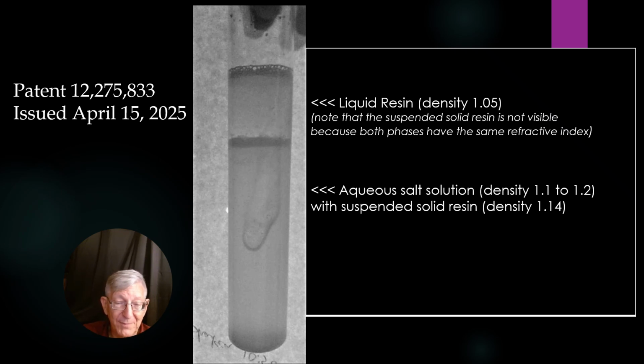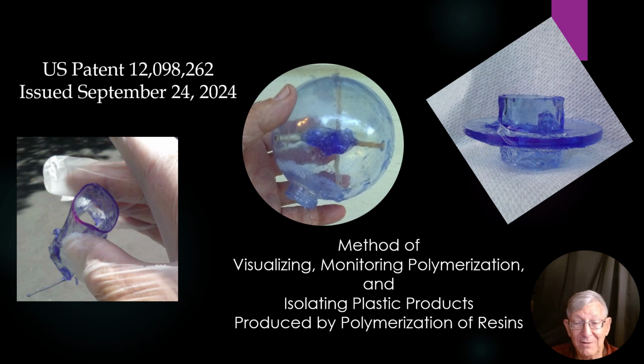Now, the other problem we've talked about is visualizing the thing we're trying to make. And the way we've solved this, and this is the other patent that we have done there, is we have discovered that you can take what we call leuco dyes, and the one that we're working with primarily is leuco crystal violet. Leuco means colorless, and so there's a form of crystal violet that is colorless, and you mix that in with the resin, and you don't notice that it's there. If the resin has reacted some and started forming solid, you do start seeing blue color, but it's typically very light, because what you're doing there is you're actually monitoring the polymerization of your resin.